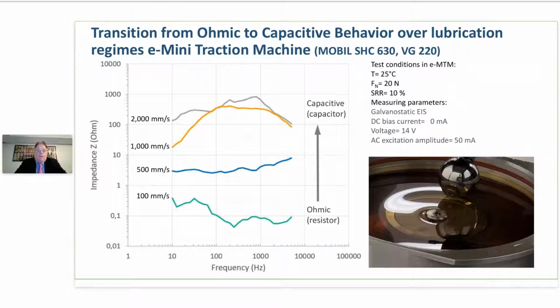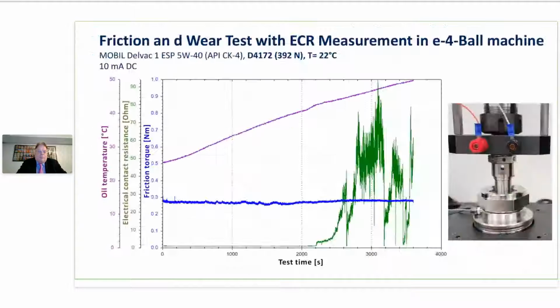So when you run, let's say, as you see here, a mini traction machine test, and you record the impedance. Impedance automatically means it is an AC current over the frequency. Then you see during the test, when you increase the sliding speed, you come from a low resistance to a high resistance because you form a film, at least a hydrodynamic film. So you have already here the range from ohmic situations to capacitive situations. This also depends on temperature and on testing time, because on the rubbing surfaces, a tribofilm with completely different properties may be formed. If you make now a 4-ball test, you have a similar situation.